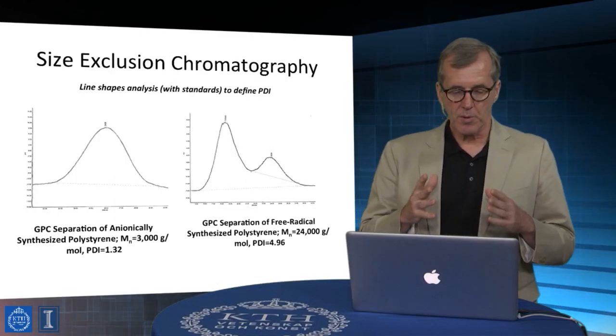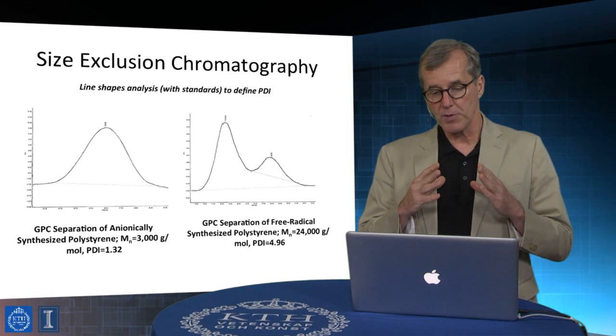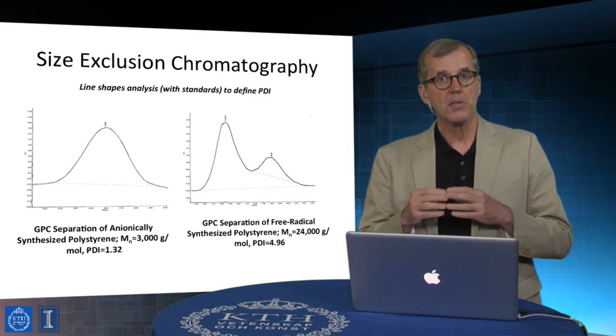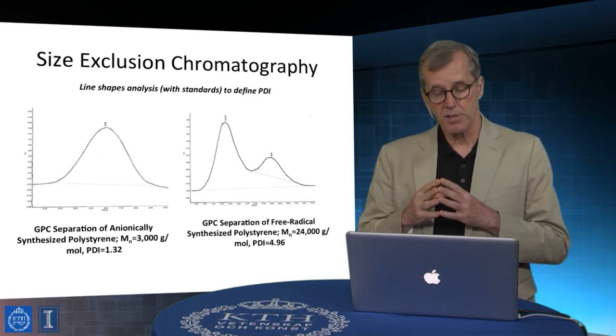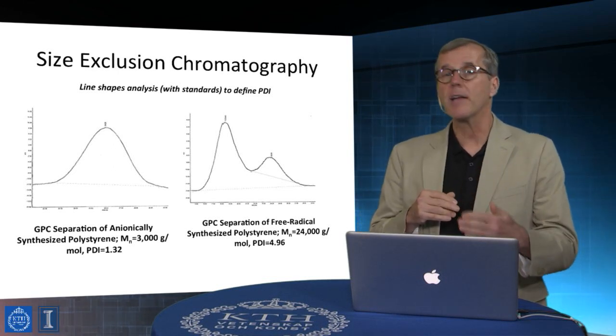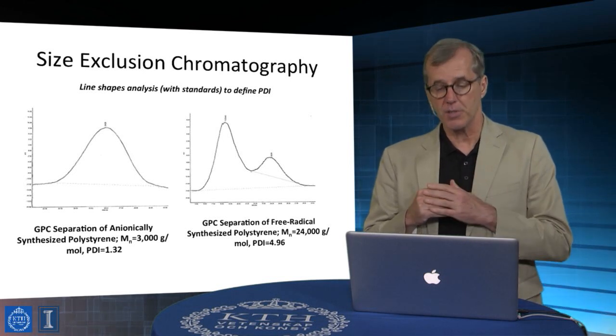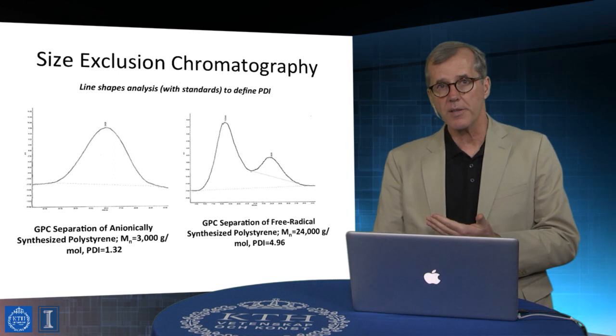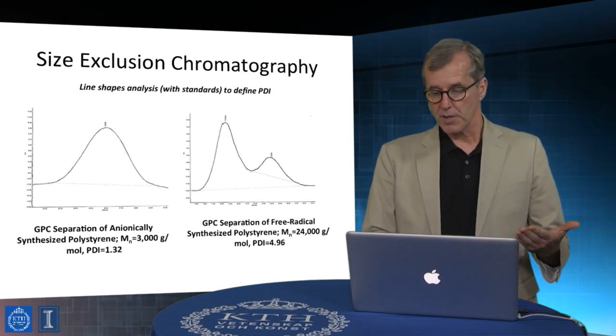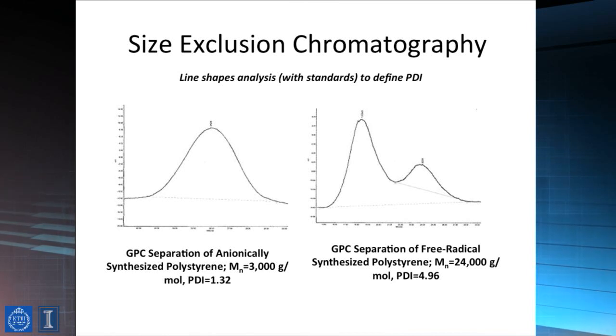And when I analyze an unknown of similar molecular weight, and if I find that the line shape is narrower or it's broader, that means that in fact the polydispersity index is different. And there's ways in which that can be quantified based on that comparison to a standard. If you look on the right side of this slide, you notice that there's an elution characteristic for a polystyrene, 24,000 molecular weight, but with a polydispersity index almost of 5. This is actually a very broad distribution of molecular weight.